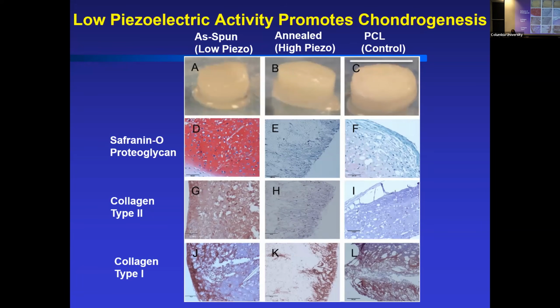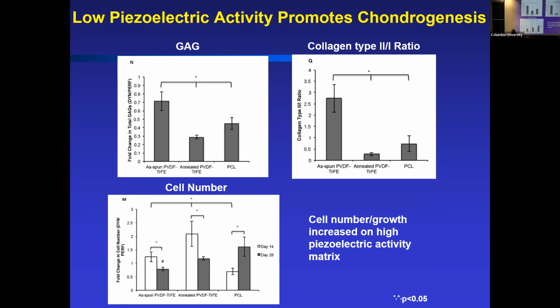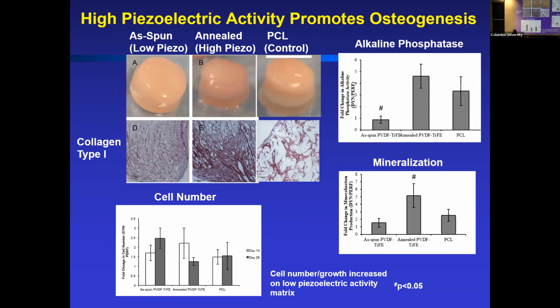And so what we found was that our low piezoelectric materials, those as-spun materials, gave us the chondrogenesis, or formation of this cartilage tissue in those bioreactors in about 28 days. So we see the nice staining of the safranin O proteoglycan, the type 2 collagen. We still had a little bit of collagen type 1 there, but not so bad, right, for 28 days just in a bioreactor. And then our annealed one, surprisingly, no, right? The high piezoelectric, we got type 1 collagen, but we weren't getting type 2 collagen, right? So that low piezoelectric material promoted that chondrogenesis and showed it with different markers as shown here. That higher piezoelectric drove more osteogenesis.